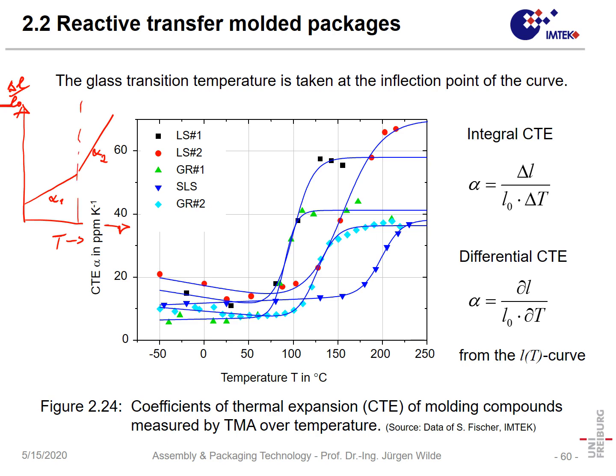And again, here we have the glass transition temperature. As when we measure the slope here, we can see in some materials, even the CTE can go down a little, but when we approach the glass transition temperature, it increases significantly, and that is similar for all materials. So in that case, we could say, simplified, the curve would be something like that. We have a low range, we have a transition range, and we have a high range. So here we have T larger Tg, here we have T lower than Tg.